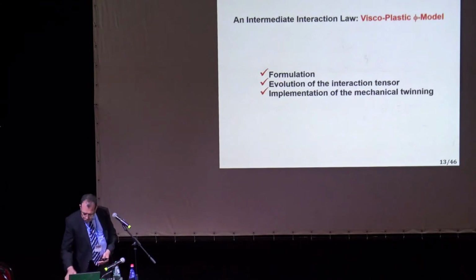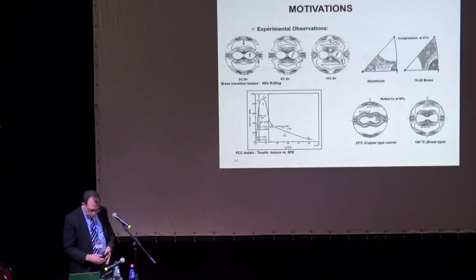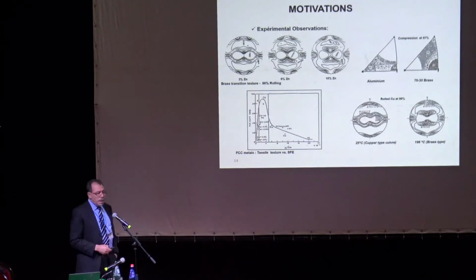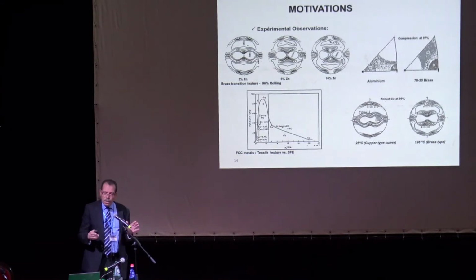And in fact, this is an example of brass and copper, or brass and aluminum, okay? So even though they are all FCC, if you take this aluminum here and look at the compression texture versus the compression texture of brass, it's completely different, okay? Even though we have this strong component similar, the distribution around here is not the same. If you look at the same again for rolling, you take copper and you take brass, you see the texture components are slightly deviated from each other, okay? What is the reason? They are all FCC, they have the same slip systems.